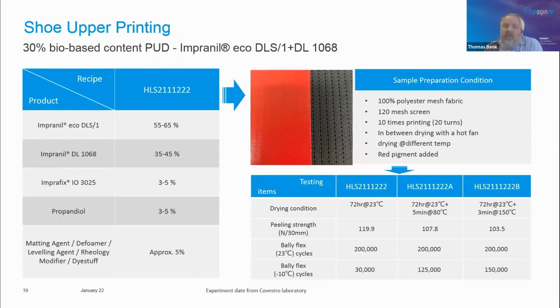Again we used different drying temperature steps. As we could observe from the results, the peeling strength did not really improve by using higher temperatures, but the cold Bally flex did improve a lot. So finally, we could arrive at a peeling strength of more than 100 Newton per 3 centimeters and a Bally flex of more than 200,000 turns at 23 degrees. And also at -10 degrees, we got a Bally flex of more than 150,000 turns.